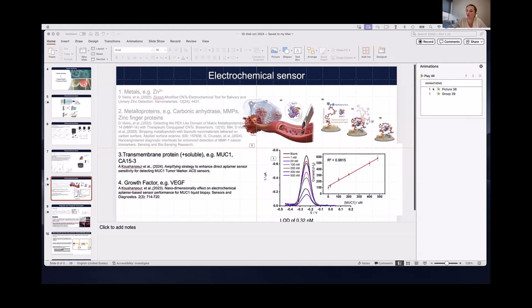So there was a PhD student, Ashkan, who worked on that. He did all his PhD on how to optimize the signal. So you want to have a very high signal. You want to measure as much as you can, and avoid all the background. And there have been lots of strategies to do that. So increasing the number of, but the problem is that it doesn't work very well. So what he did, his strategy was, instead of what usually people do, they only put one redox molecule. So it's going to have, let's say, one electron transfer. So what he did, he added two. So we did some chemistry on top of this DNA, and we attached two molecules instead of one.